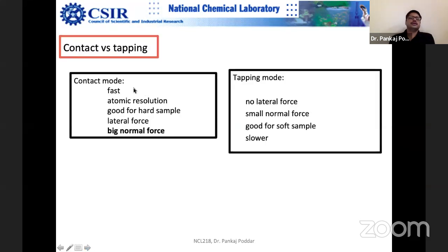So to summarize, contact mode is fast. It has good resolution and is good for hard samples. Lateral force is there, and a big normal force because you are all the time almost scratching the surface, depending upon your set point and gain. Tapping mode has no lateral force, a very small normal force, and is good for soft samples, but it is slower and the resolution is much lower. But in contact mode, resolution may be compromised, this may become bad because of this normal force, because the normal force is very high.